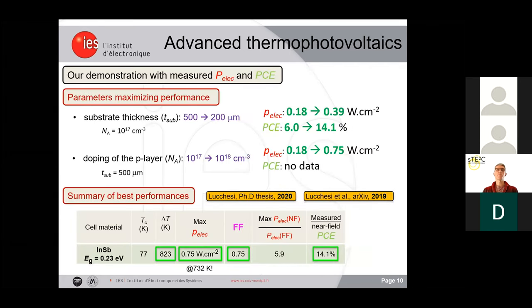So what are the parameters maximizing performance? We made measurements for two different substrate thicknesses, and thinning out the substrate improves the electrical power as well as the power conversion efficiency. Increasing the doping concentration of the P layer of the PV cell increases the electrical power, but we couldn't get any data for the efficiency.